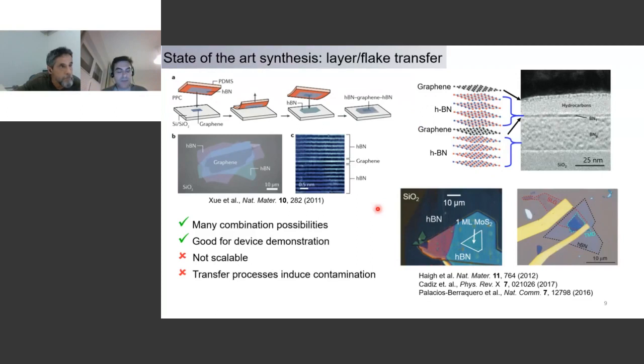This is quite nice. This allows you to have many combination possibilities. You can play around a lot for basic investigation. It's quite interesting, and very good for device demonstration, but you also have many problems. One of the problems is, of course, scale. I show you here many examples where basically you see micrometer sized flakes and structures that have been produced. And in addition, what's usually observed is that, even if you do that quite well in a glove box and so on, you may end up with some contamination at the interface.